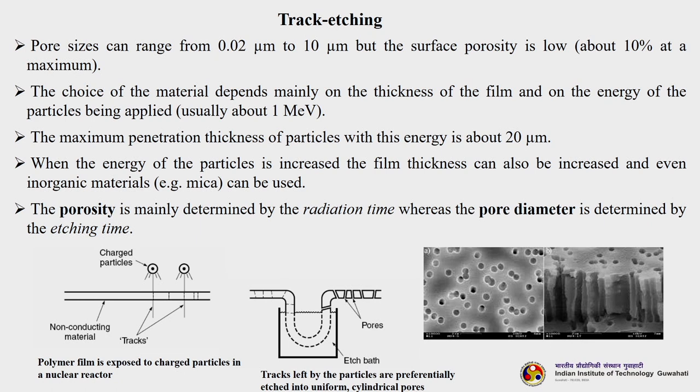So, the porosity is mainly determined by the radiation time, okay, whereas pore diameter is determined by the etching time, okay. So, etching is done to remove whatever loose or adhered particles are attached to the track, okay, then the pores will be cleaned.